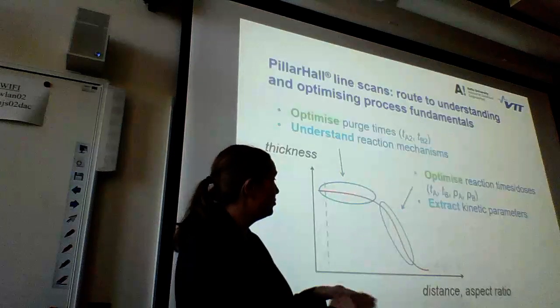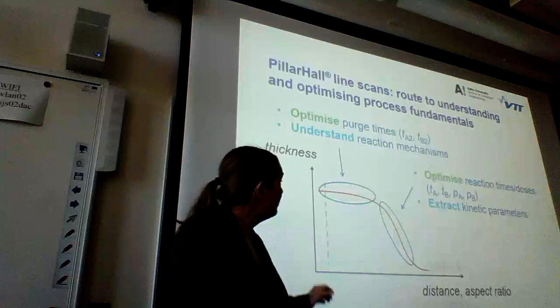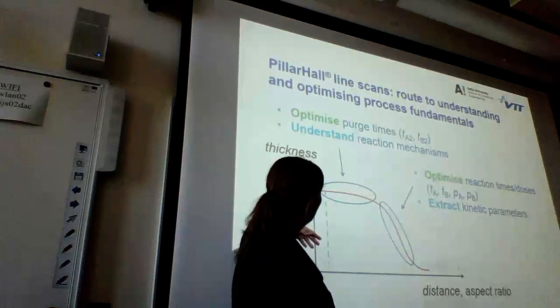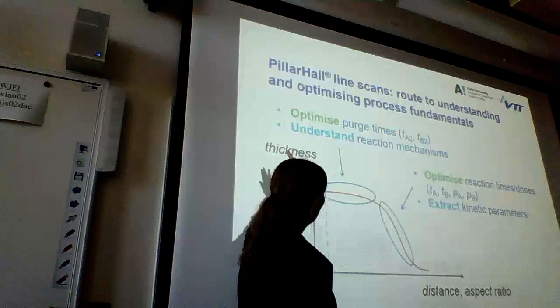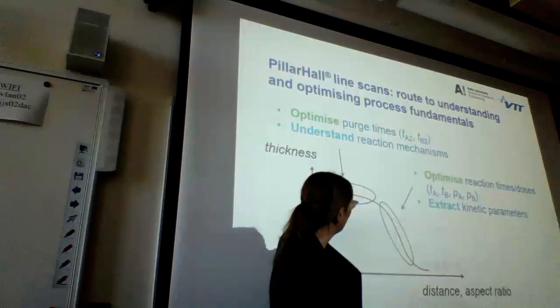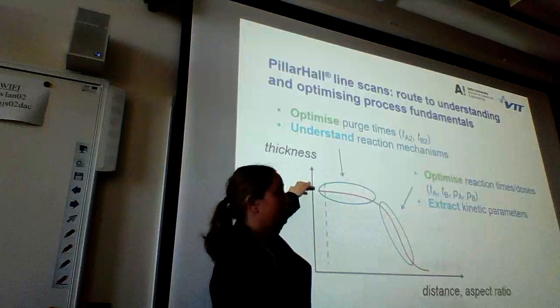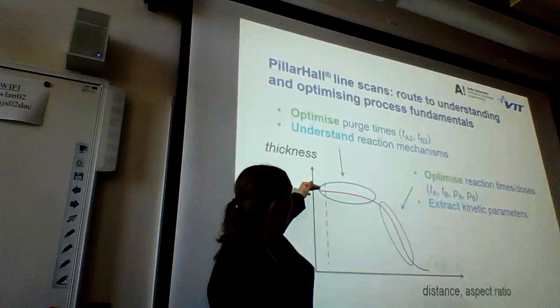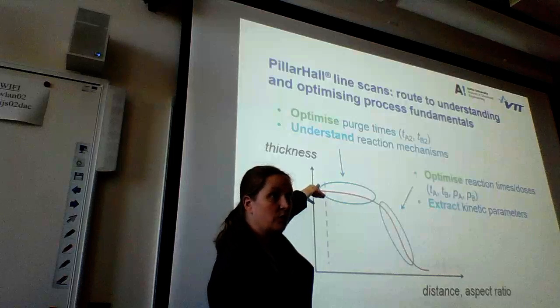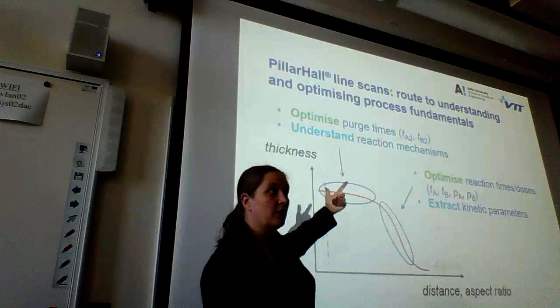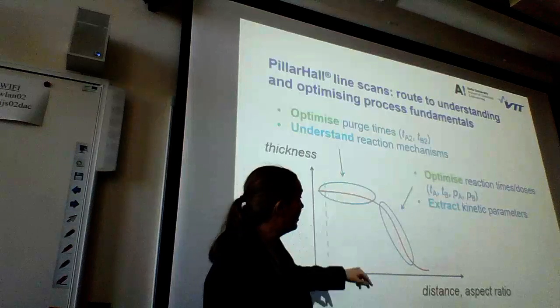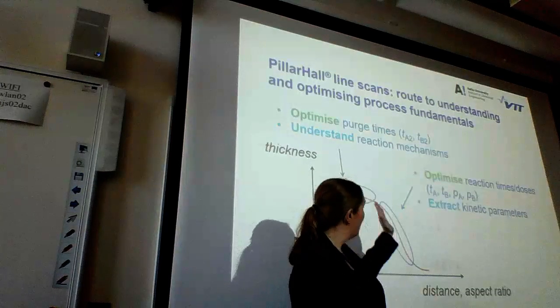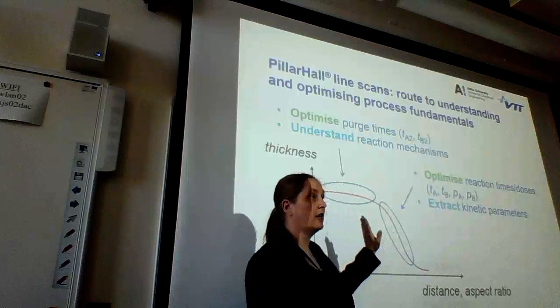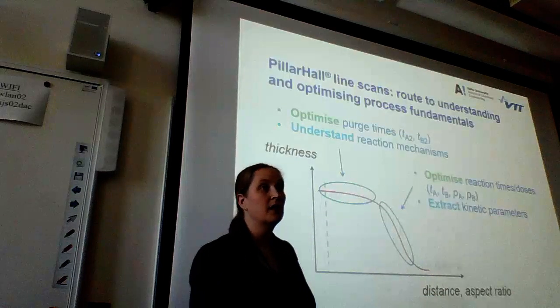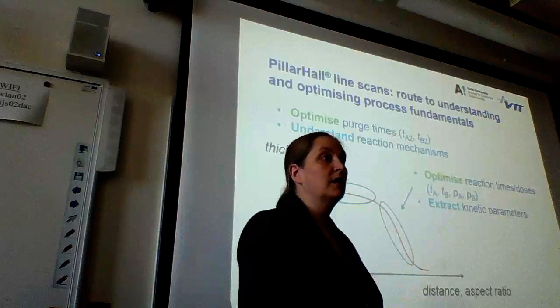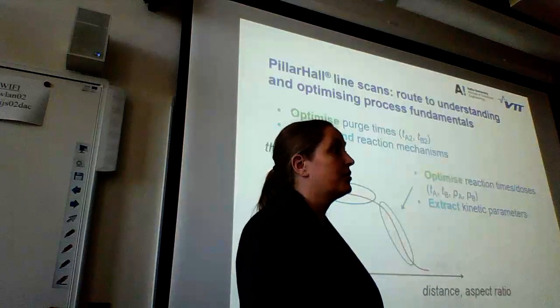Here we can use these automatic mapping methods and get very, very detailed information with which you can, of course, if you know how far the film goes, optimize your purge times. You can understand the reaction mechanism also if you look at this, because TMA water has a flat plateau here, but not all films will actually be flat. So you get to these questions: is it irreversible, is it saturating, and what are the kinetic parameters of the reaction? So how steep the slope is will be related to the fundamental kinetics. I think that this will open up a lot of new avenues for research.